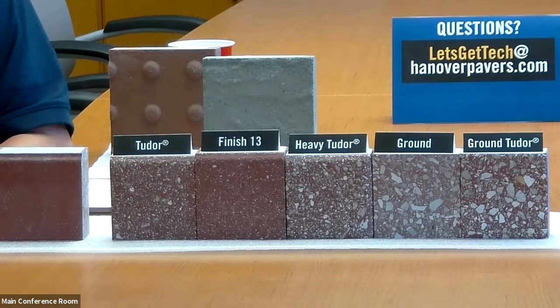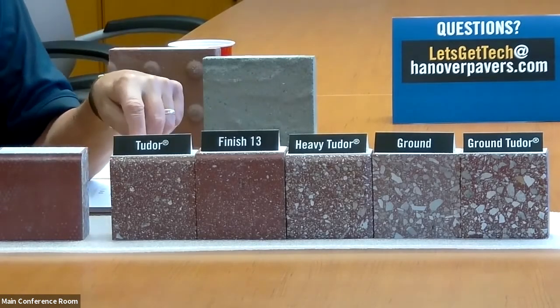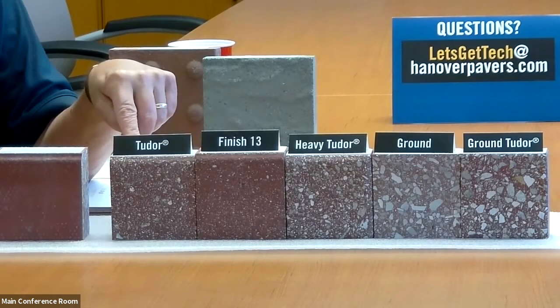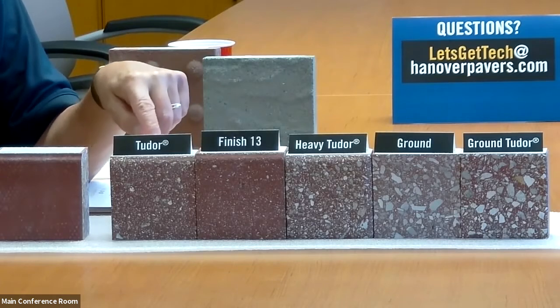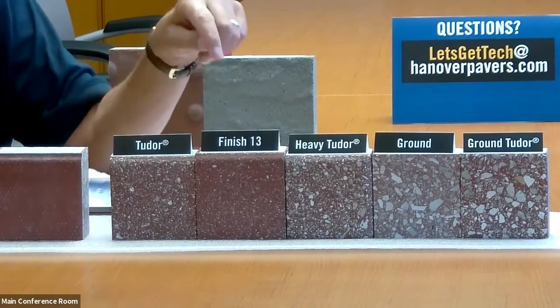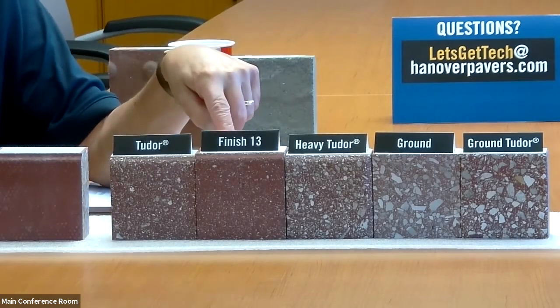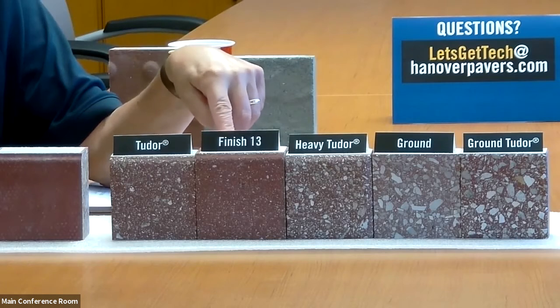Options that we have for exposing that aggregate: we can sandblast it, and with the blasting process, we can actually control the intensity of the blast. So we can expose more aggregate or less aggregate. Here's an example of what we call Tudor finish, which is probably our meat and potatoes, where we just blast the surface of the unit and expose the aggregate. Some people don't want to see that much aggregate, so we can also do what we call finish 13. Same process, we just don't hit it as hard and expose as much of the aggregate in the mix.